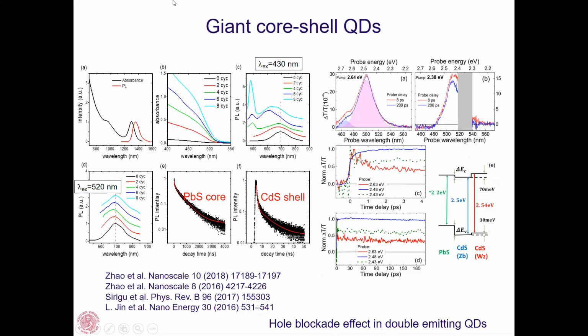When we excite at 430, we have an emission around 490-500, which comes from the near band edge emission of the cadmium sulfide shell, and an emission around 700 nanometers, which comes from the lead sulfide core. This is confirmed by the lifetime of these two emissions, which is in the microsecond range for the lead sulfide core, and tens of nanoseconds for the cadmium sulfide shell.